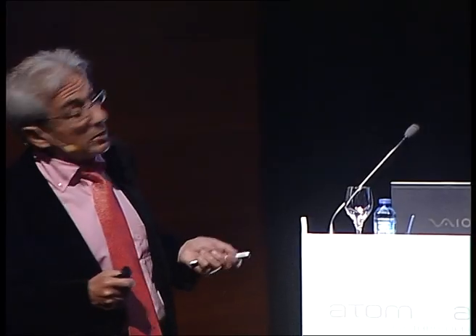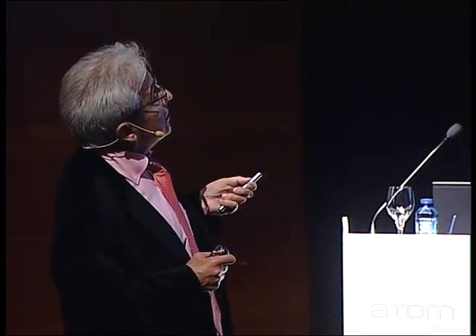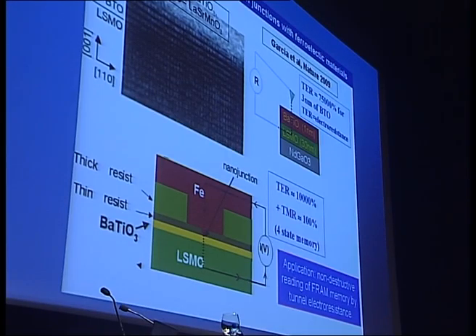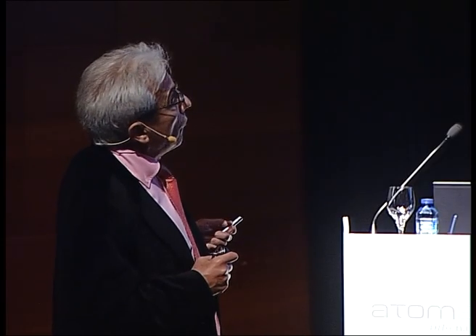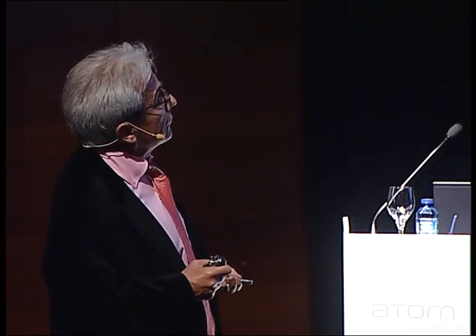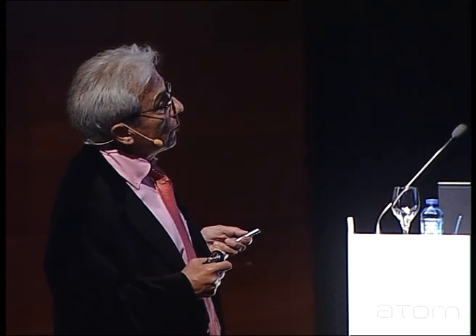And for example, we have also extended our expertise to the fabrication of tunnel junctions with ferroelectrics instead of ferromagnetics. For example, BTO, this oxide, which is a well-known ferroelectric material. And what has been found is that by growing this layer very carefully, it was possible to obtain the ferroelectric property even for very small thickness, 2 or 3 nanometers of these materials, and finally to fabricate tunnel junctions with a ferroelectric barrier, for example, this tunnel junction.